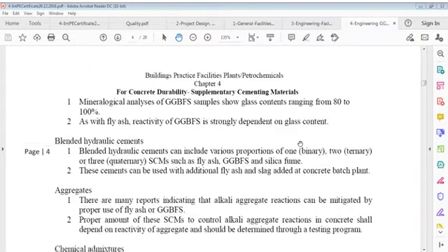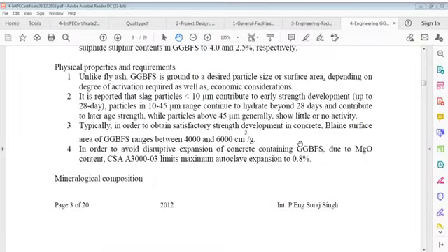Physical properties and requirements: unlike fly ash, GGBS is ground to the desired particle size or surface area depending on degree of activation required, as well as economic considerations. It is reported that slag particles less than 10 microns contribute to early strength development up to 28 days. Particles in the 10 to 45 micron range continue to hydrate beyond 28 days and contribute to later age strength, while particles above 45 microns generally show little or no activity, typically in order to obtain satisfactory strength development in concrete. Blaine surface area of GGBS ranges between 4,000 to 6,000 centimeters square per gram.